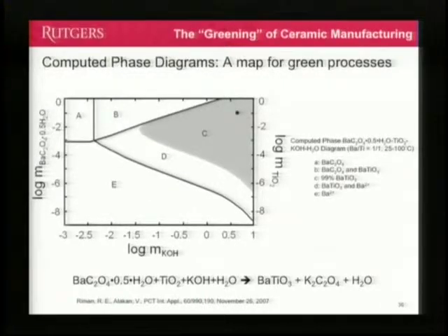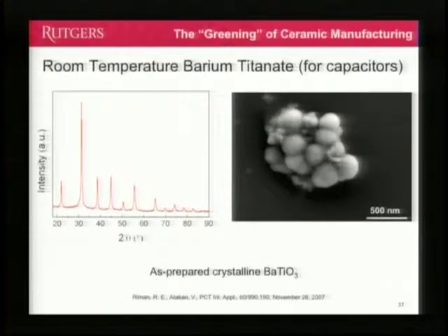So we were dying to find out if this thing actually worked. And lo and behold, in a few minutes, you can make barium titanate straight from the same raw material that industry says can only be done at high temperature and milled. And here's some examples of the powders. This is a very good first result that shows we can make the particles small and spherical, and from here we can optimize a lot of the process.